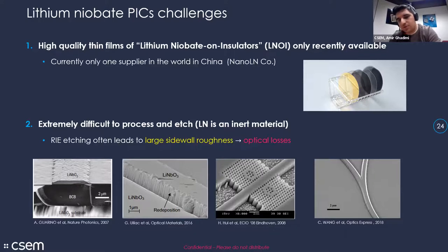The other challenge is patterning and processing of lithium niobate. Lithium niobate is known as an inert material. It doesn't interact with acids or bases, nor can HF etch it. So it's a very difficult material to process. I cite a few attempts in the literature, and you can see that many people, when they attempt to etch it, create a huge amount of edge roughness, which leads to major optical losses.